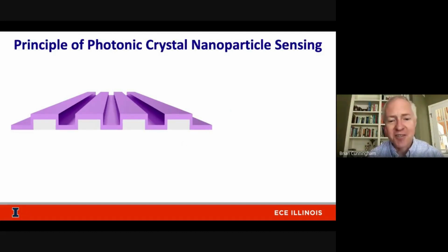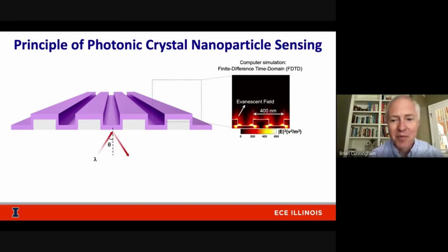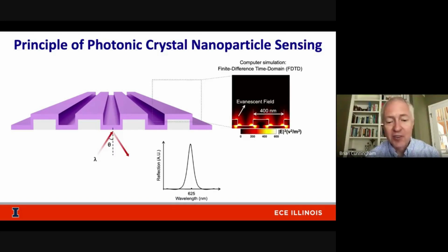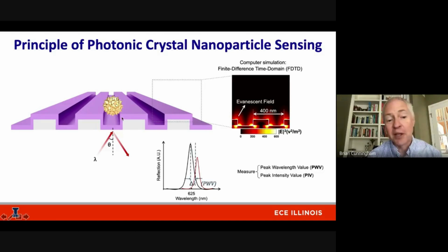So we sought to take advantage of that basic electromagnetics effect in the following way. If we have a photonic crystal surface, it has its resonance at the 625 nanometer wavelength range if we don't put any nanoparticles on it. But now let's say we take a gold nano-urchin and we attach it to the photonic crystal. What we observe is that two things happen. First, the gold nano-urchin has replaced some of the water that used to be there, and so the resonance wavelength of the photonic crystal will shift from a lower value to a larger value. We call that a shift in the peak wavelength value. But also, and most importantly for us, the absorption of that gold nanoparticle will rob away some of the photonic crystal's resonance energy, and the reflected intensity will go down.